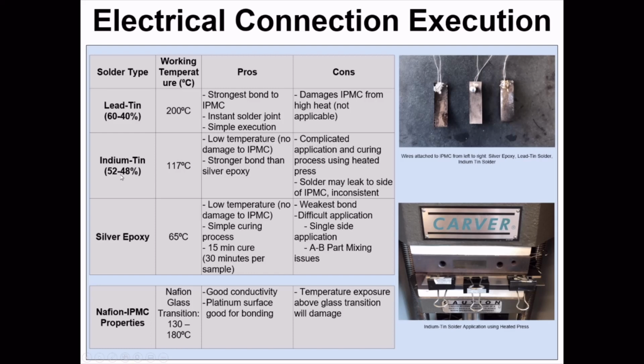So our last attempt was indium tin solder, and that's what this process is right here, and this film right here. And this was really good. It was strong, much stronger than silver epoxy, but it was really difficult to use because you had to get the film and everything to this exact temperature of 117 C.